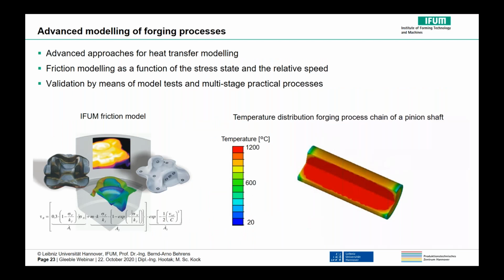Two further topics deal with friction and tool wear in hot bulk forming. The friction in the massive forming process is, for example, mainly driven by the contact pressure and the relative speed between workpiece and tool surfaces. In recent years, the so-called IFUM friction model has been developed, which takes these two physical parameters into account. This friction model has even been integrated into the commercial software Simufact Forming and is therefore available to numerous users.